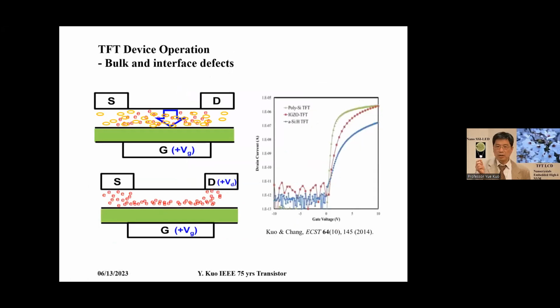So the TFT is based on the same operating principle as a MOSFET, but the difference is this. For TFT, all the films are deposited, usually at low temperature, because glass is used as the substrate. Glass usually cannot stand more than 400 degrees C, typically less than 350 degrees C. So the deposited film is very different from silicon film. For example, the semiconductor itself is full of defects. The defects are charge trapping sites, traps. For polysilicon, the traps are defects in the grain and grain boundary. For amorphous silicon, the traps are, for example, dangling bonds.